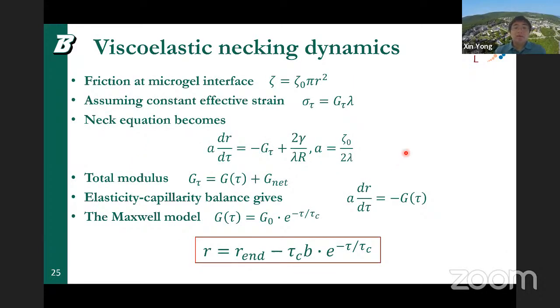And then we can further work on some mathematics here by making several assumptions. First of all, consider frictions are concentrated in the neck region. Therefore, it's proportional to the size of the neck. And then we also assume the change is relatively small, so it's a linear elastic regime where we consider the strain is constant. And so then the whole neck equation will become basically balanced by the dynamic elastic modulus and a surface tension contribution. And from the presence of the final steady state neck, we know that these two contributions will ultimately balance each other, because that's how you get zero variation in the radius.